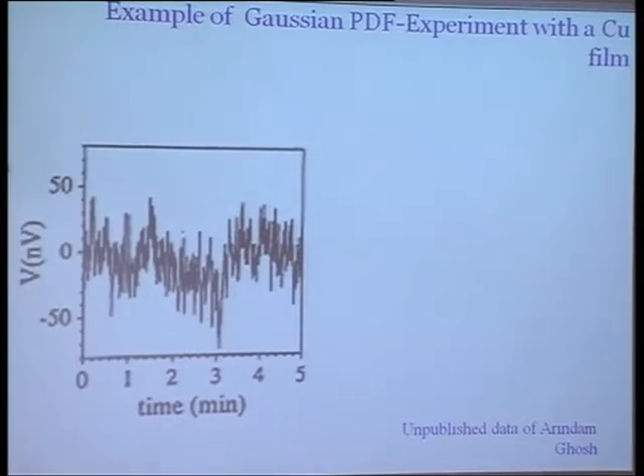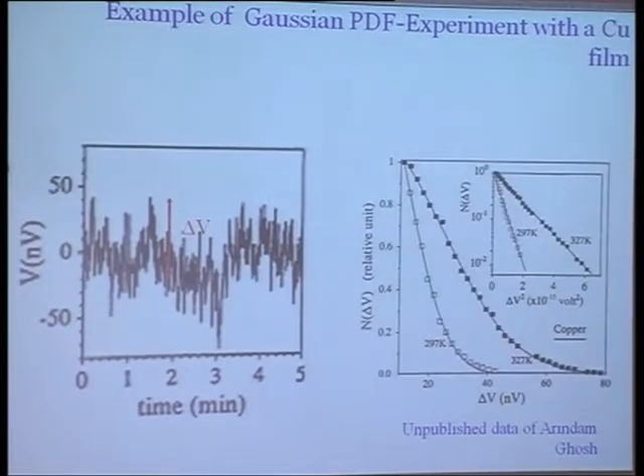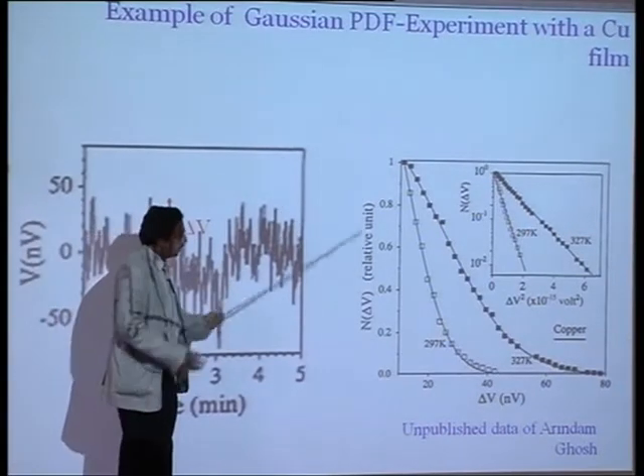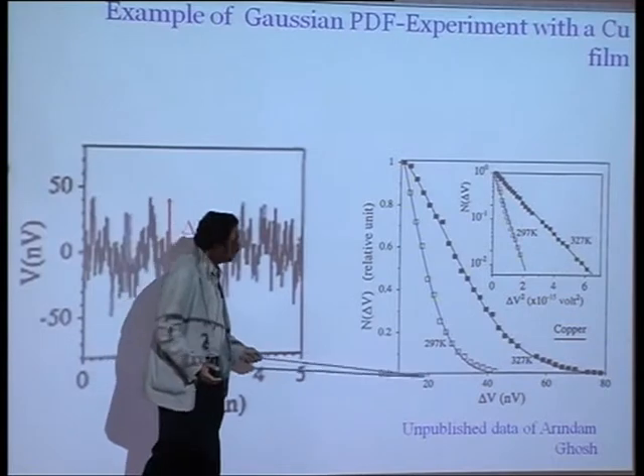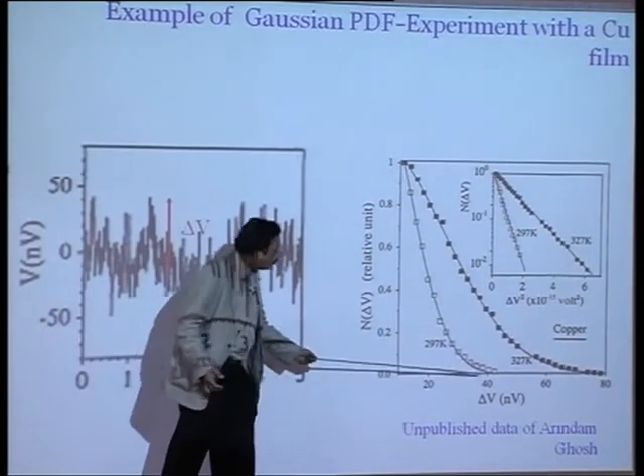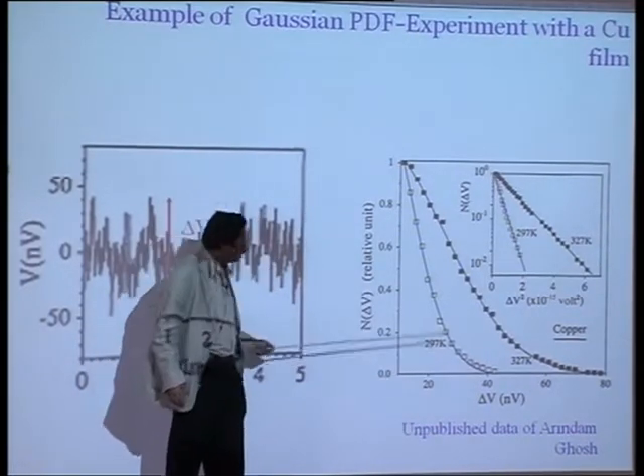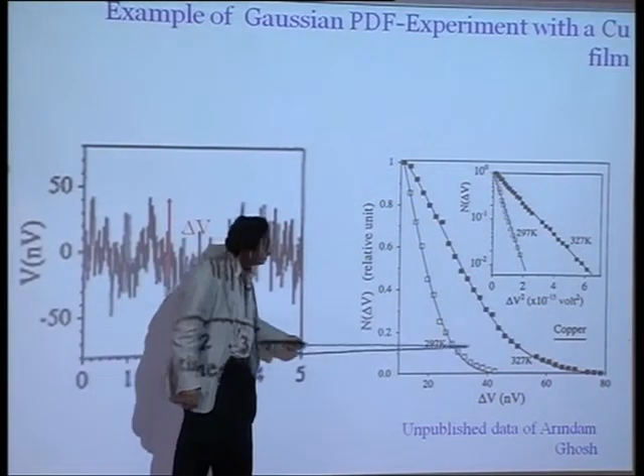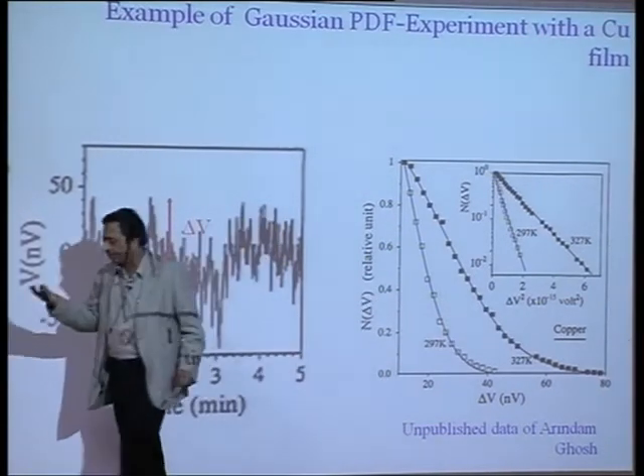So now, suppose this is real data in a copper film. You subtract out the average voltage and you get this voltage fluctuation, and this is the typical voltage fluctuation that you see. Then if you take that voltage fluctuation and plot a probability distribution, you say, okay, I have 20 nanovolt fluctuations, so many numbers, 40 nanovolt fluctuations, so many numbers, and all that. And you can see that as the temperature is increasing, the width of this fluctuation is going up.